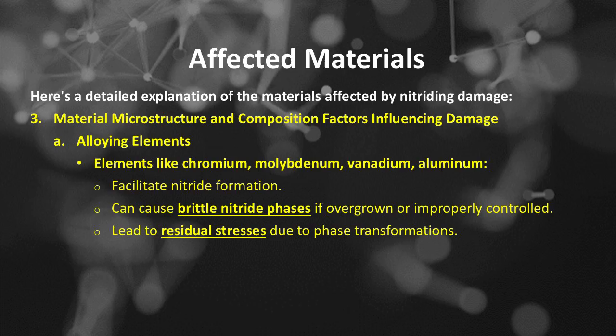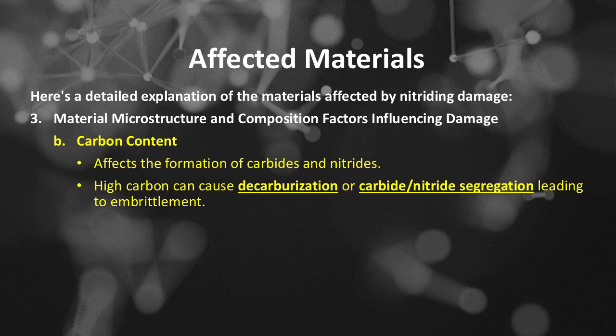Number 3 of the materials affected by nitriding damage is material microstructure and composition factors influencing damage. Number A, alloying elements. Elements like chromium, molybdenum, vanadium, and aluminum facilitate nitride formation, but can cause brittle nitride phases if overgrown or improperly controlled, leading to residual stresses due to phase transformations. Number B, carbon content, affects the formation of carbides and nitrides. High carbon can cause decarburization or carbide/nitride segregation leading to embrittlement.